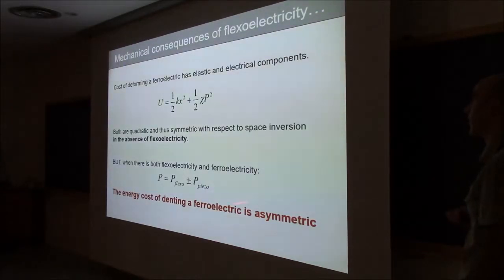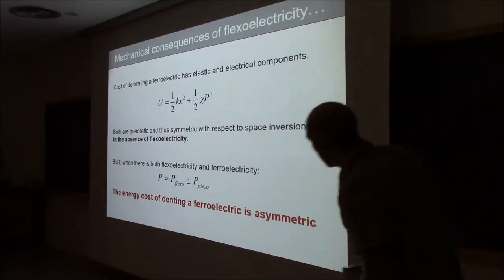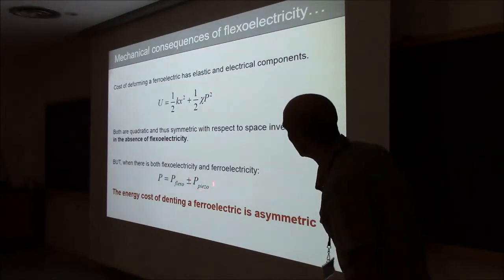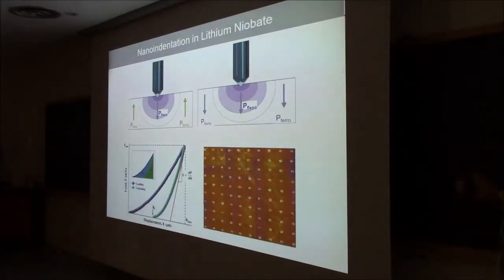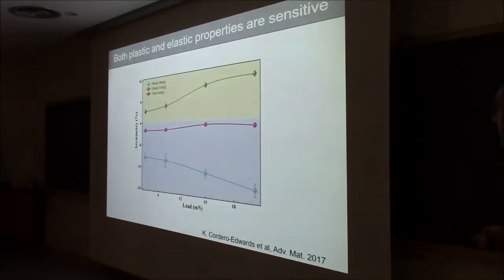So this is, hopefully, if you are sufficiently awake, you will understand, or at least believe, that the cost of deformation does depend on the polarity of your ferroelectric, because the piezoelectric polarization can be additional to or subtracted from the flexoelectric polarization. You can measure this effect by doing indentation. We have, and indeed it is asymmetric.